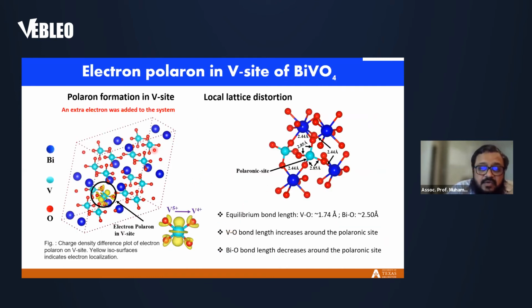We form an electron polaron on the vanadium side, the way we described it 2-3 slides ago. The first thing, again, is that the electron polaron is localized at a vanadium site, and this is how the charge density looks, a magnified view. And definitely, because of the charge trapping, electron trapping, the charge state of the vanadium atom changes, and these are the corresponding lattice distortions around that vanadium atom. Both of these are the footprint of polaron formation.